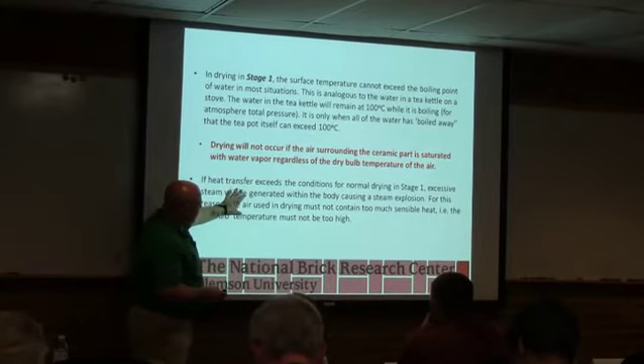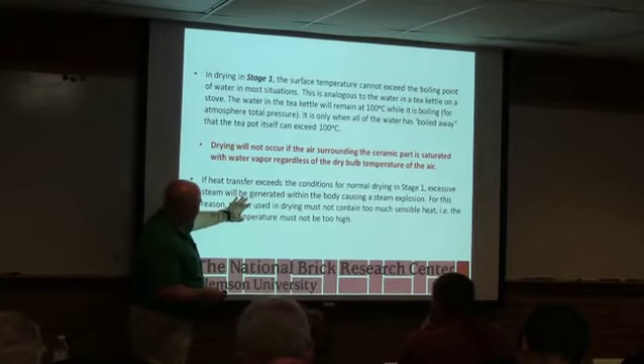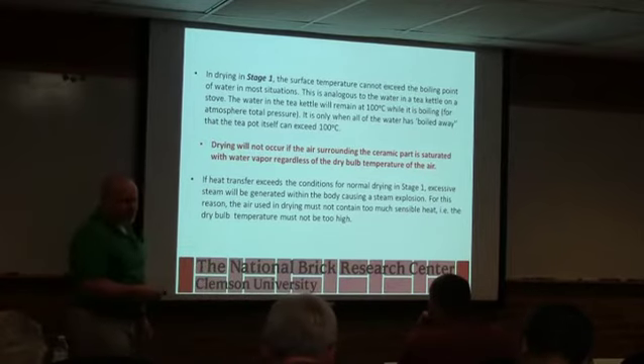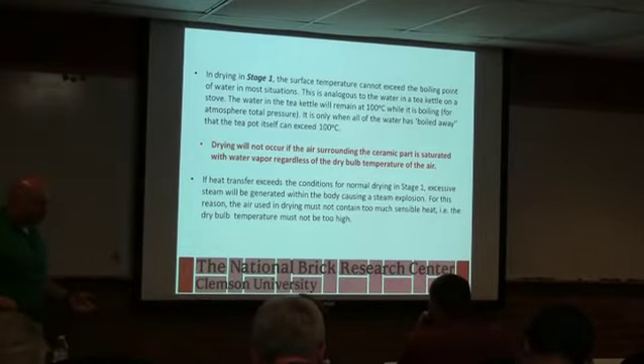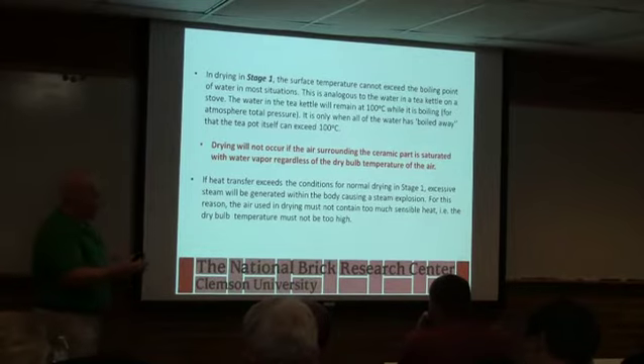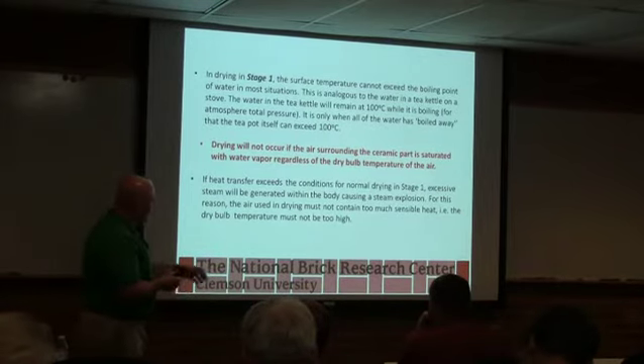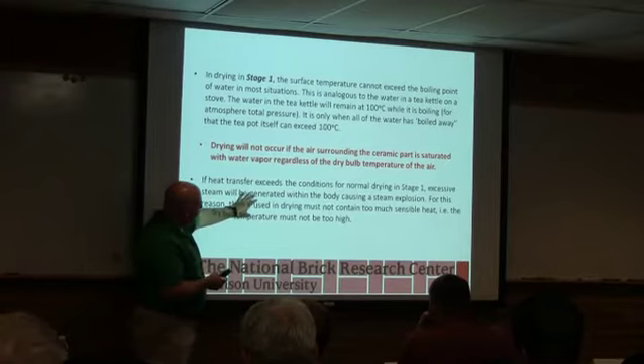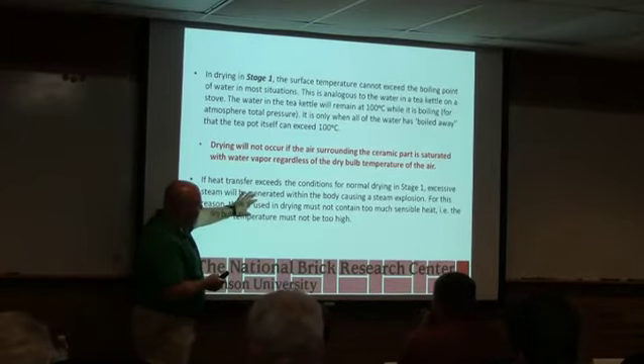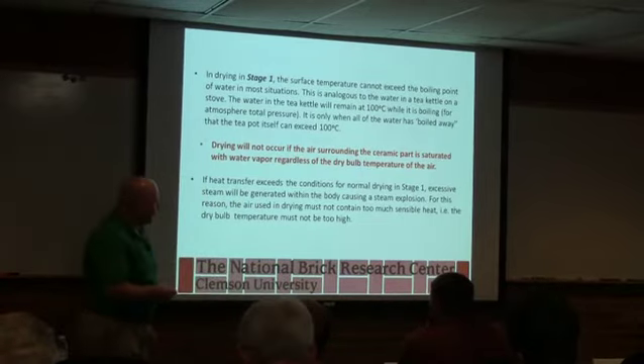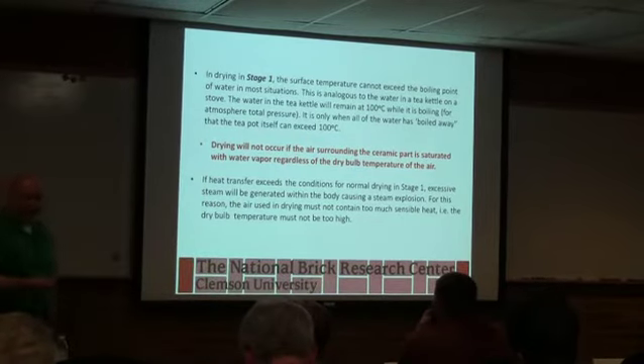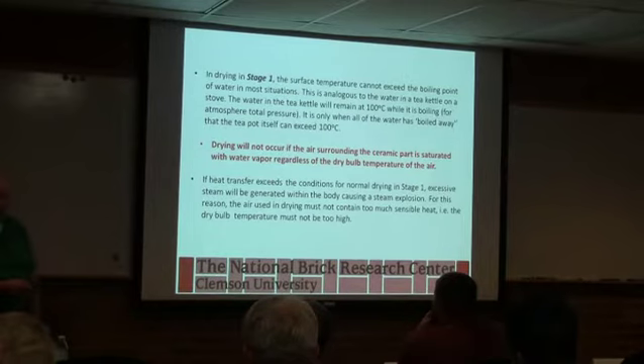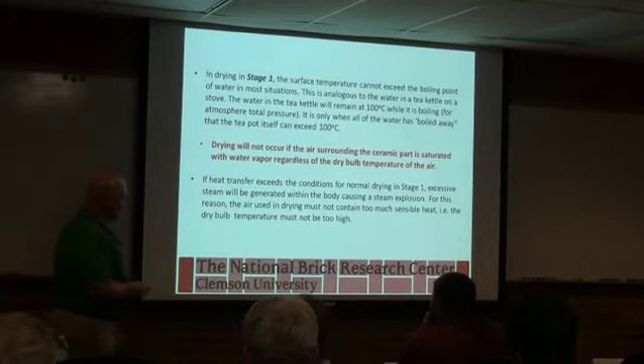So in stage 1, what we're trying to do is not develop excessive steam pressure in the pores. Okay, so we're pushing water up to the surface to evaporate, and if we create too much of a driving force, we create excessive pressure, and you can get steam spalling or explosions. Anybody ever done that where you popped brick in the dryer? No? Okay. I've done it in the lab a few times.